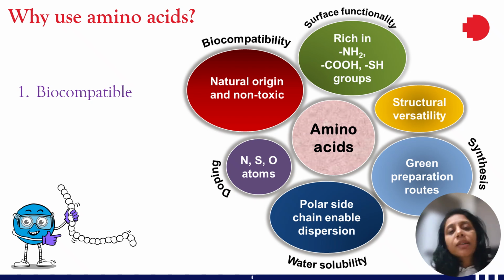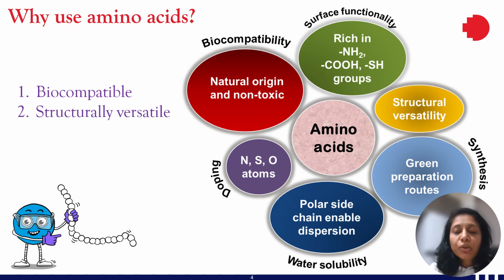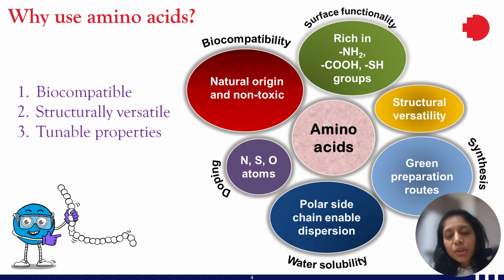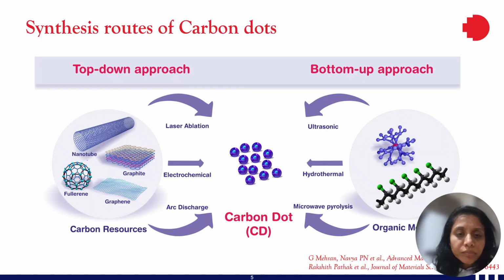Secondly, amino acids are chemically rich. They contain functional groups such as carboxyls, amines, and side chain elements like nitrogen and sulfur. These heteroatoms get incorporated into the carbon core during the synthesis process, which allows us to achieve heteroatom doping and surface functionality in a single step. And the third reason is that the choice of amino acids gives us control over the properties of carbon dots. Different amino acids lead to carbon dots with tunable fluorescence and dispersibility.